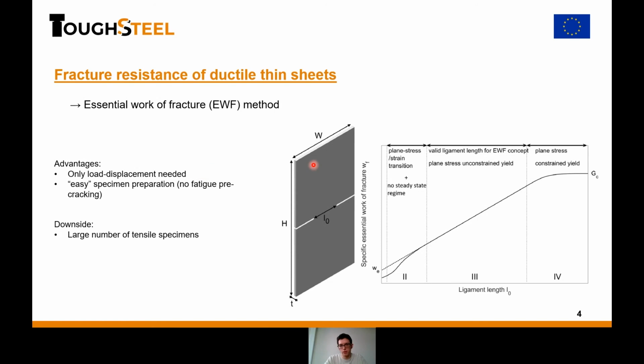The principle of the method has been gone over by David and Thomas already, so I will go fast about this. Inside the valid range of ligament length, you find this linear behavior and extract the constant term, which is the specific essential work of fracture, directly linked to your damage and fracture behavior. But to do this, you need to measure the total work for several ligament lengths. That means you need a large number of tensile specimens.